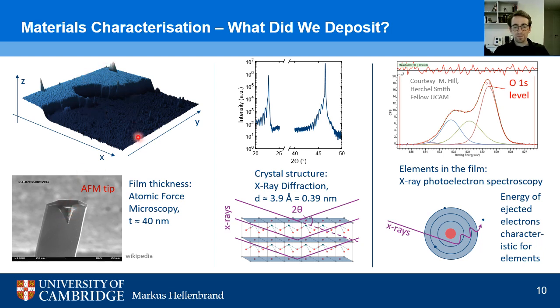on the film. So in this example, we see that the thickness of the film, so the height of the step here from the substrate where we deposited the oxide to the oxide itself, was about 40 nanometers. That means this technique has a very high sensitivity on the nanometer level. So with this, again, we can detect the roughness and the thickness of our film, but of course we also want to make sure that we have the correct composition.